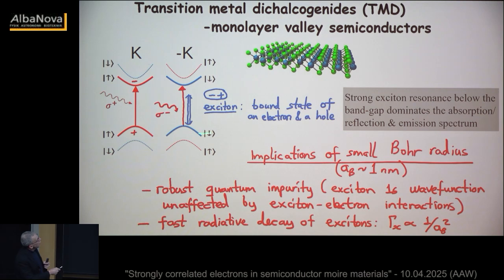Now, I told you about the exciton. In gallium arsenide, the exciton Bohr radius is 10 nanometer because of the large dielectric screening and light mass. Here the Bohr radius is about 1 nanometer. So interactions are substantially stronger in this material system. The binding energy, even with dielectric encapsulation, is about 230 millielectron volts. So these are really tightly bound objects.